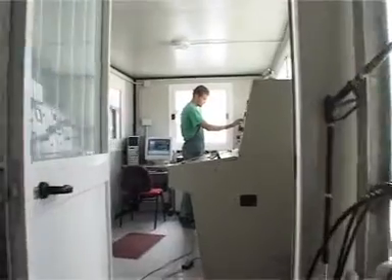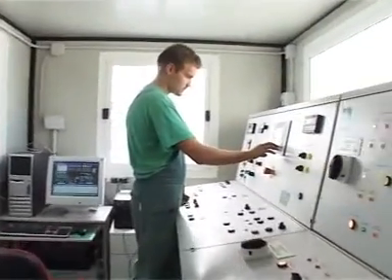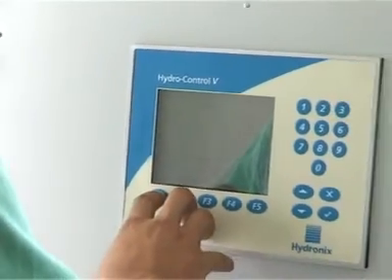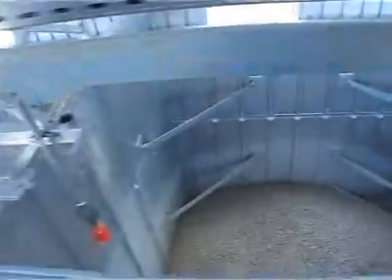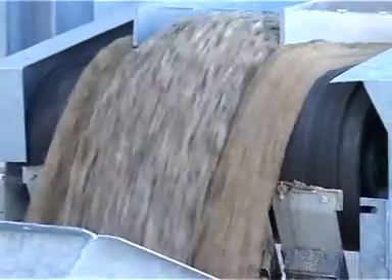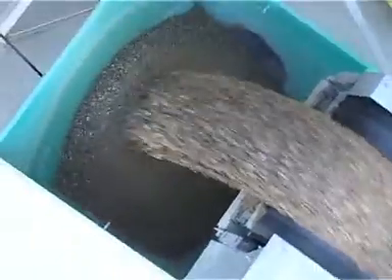An important aspect in the production of pre-stressed concrete elements is the batching plant, which has the important task of supplying a homogeneous mix of sand, gravel, cement and water at a constant humidity. A series of probes situated in the hoppers and in the mixer constantly monitor the aggregate, whilst a computerized management system controls the ratio and humidity of the aggregates in order to meet the specifications required.